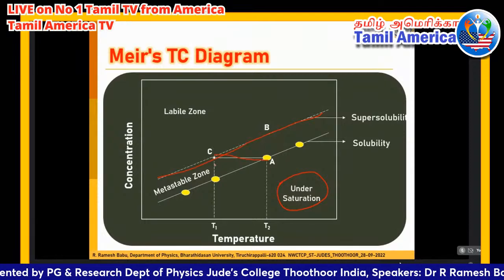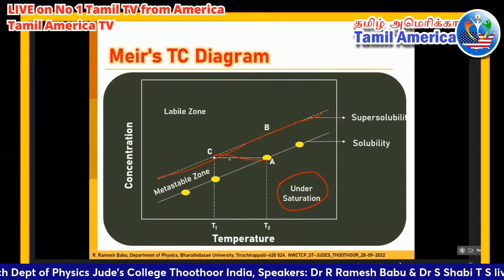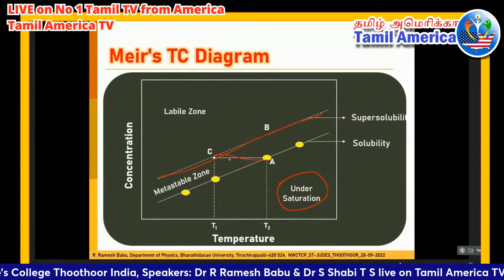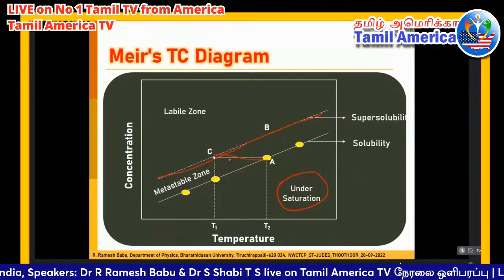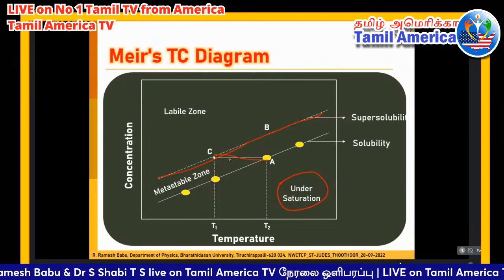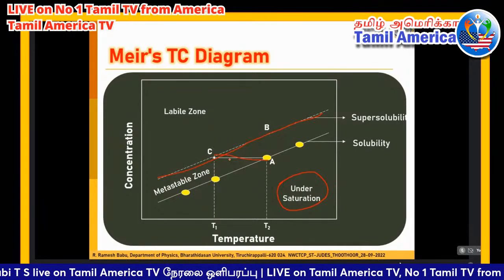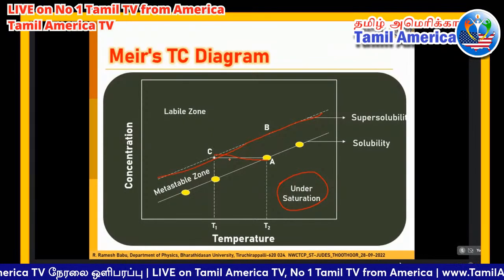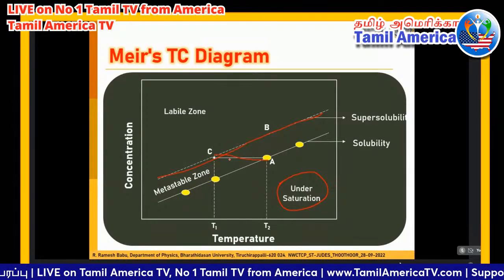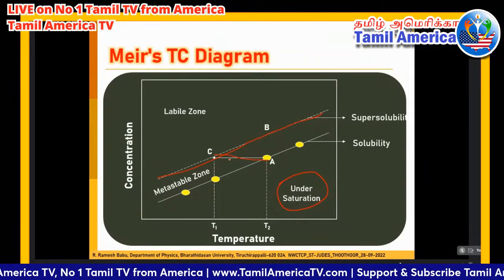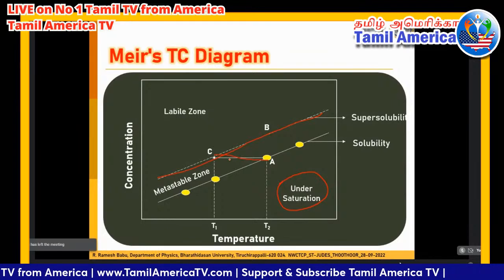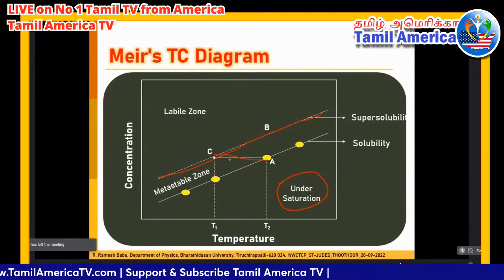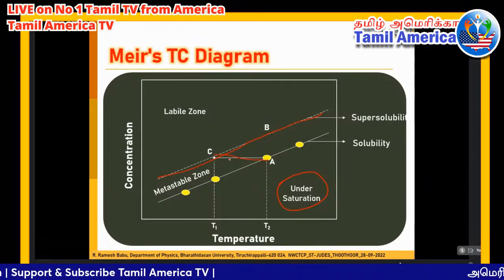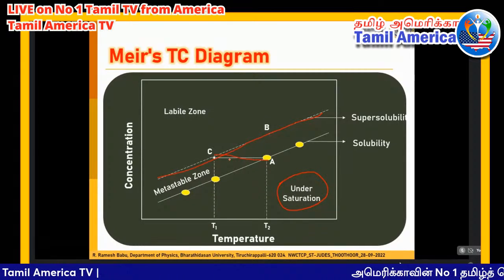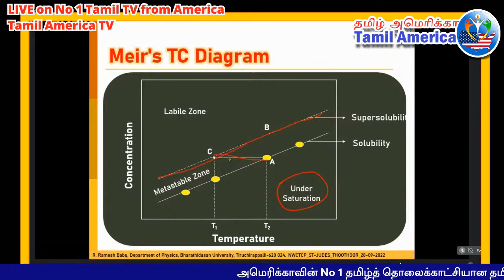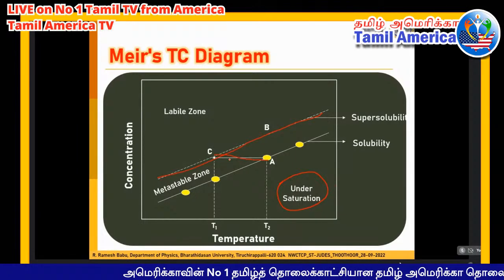Any one temperature in this metastable zone, you can start to grow a good quality single crystal. Mostly with these solution growth techniques, very many single crystals are grown worldwide, even bulk single crystals for fusion experiments, grown by different researchers. Even KDP single crystals are grown by these simple solution techniques. They used the metastable zone width to grow bulk single crystals with fewer defects.